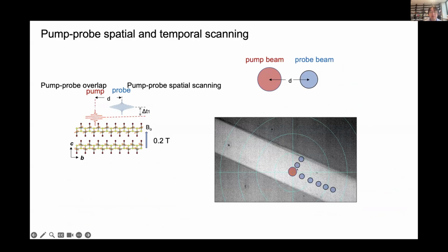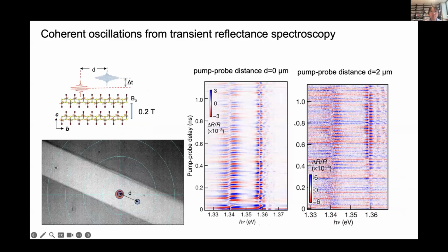And so we placed the probe beam along several different positions. And you can see that when we place our probe beam exactly at the pump spot, we will see the wave generating instantaneously as we excite. But if we move the probe further away, it takes time for the waves that were generated at the pump spot to get to that spot. So what we see is that there's no signal at first, and then we start to see a signal from the exciton energy being modulated.